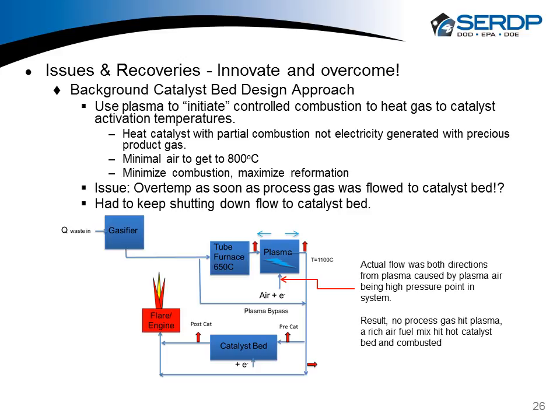And the issue that we had, when we were doing these experiments with the catalyst bed, was overheating. And that should be an endothermic process, the catalyst process. But as soon as we had the process gas open to it, we were very rapidly getting 800, 900, 1,000 degrees, and we basically panicked and thought, wow, this is bad, we better shut down.